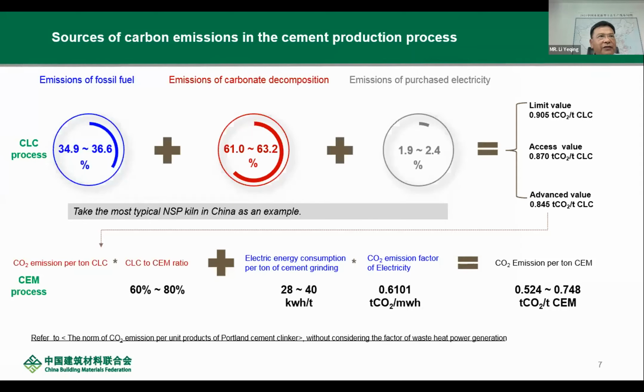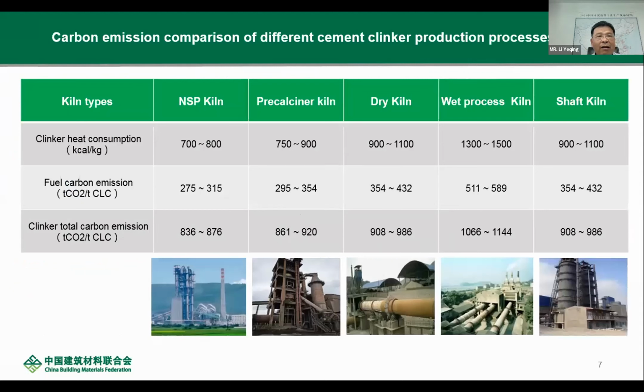This calculation is based on the China average. The power emissions factor is 0.61. Therefore, the carbon emissions of the whole cement process are about 524 to 748 kilograms per ton cement. The mentioned data is based on the NSP kiln.